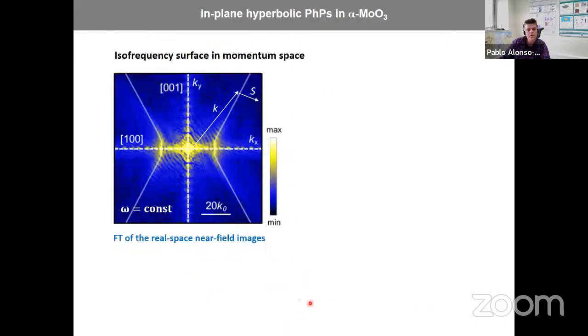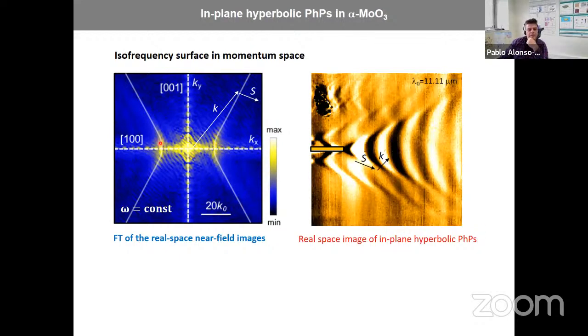Okay, so let me come back to this property. You have an infinite number of k's here along this asymptote, but there is also another property, which is that by definition, the Poynting vector of the wave is normal to the isofrequency curve. So typically in isotropic media, you have a circle here, and k and S are collinear. So the wavefronts, right, they are plane waves, and the energy goes exactly along the normal of the wavefronts. But in this case, it is different.